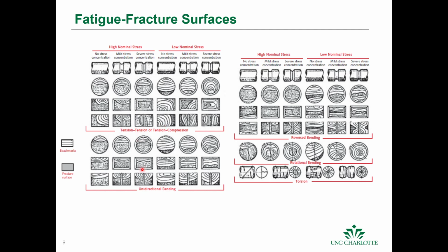And down here, this is from one directional bending. So this would be bending down in this direction. And you can see the crack propagates until you get to a certain point in this gray area in all these graphs. This is when the surface fractures. And you can see it for different geometries and different loading conditions. And you can see here that if you have reversed bending, then the cracks will propagate from both sides.